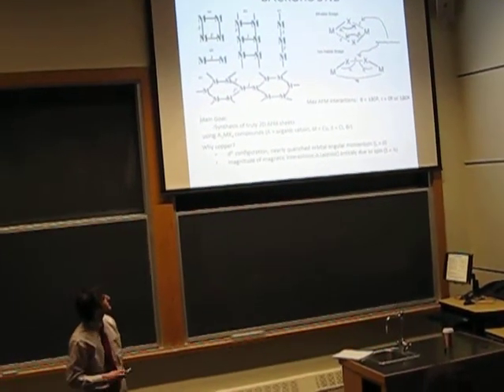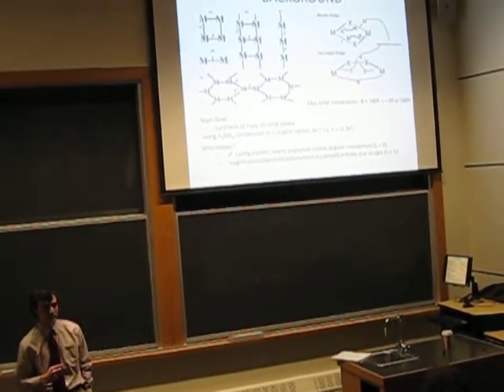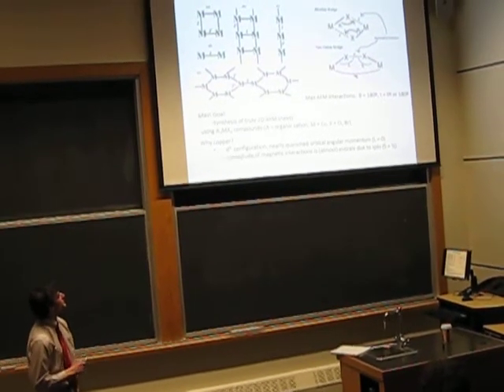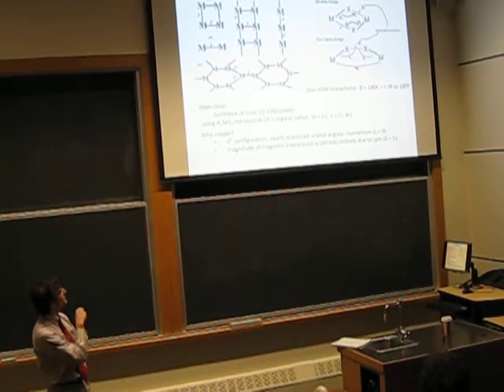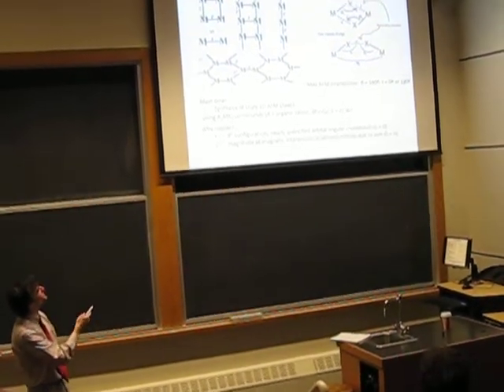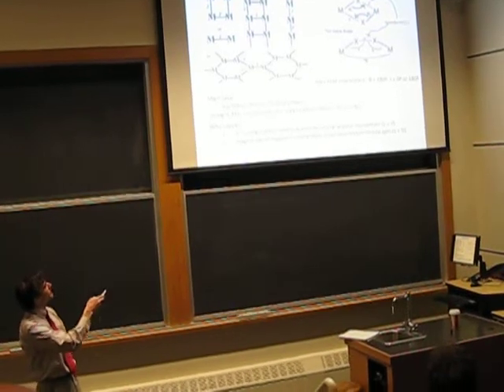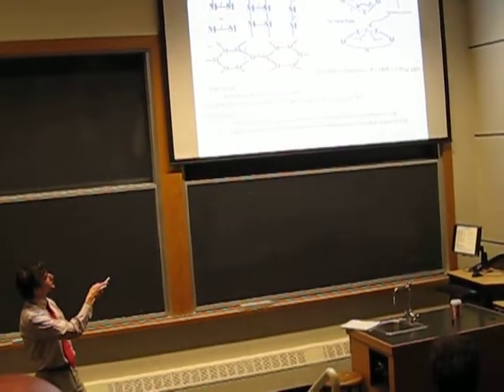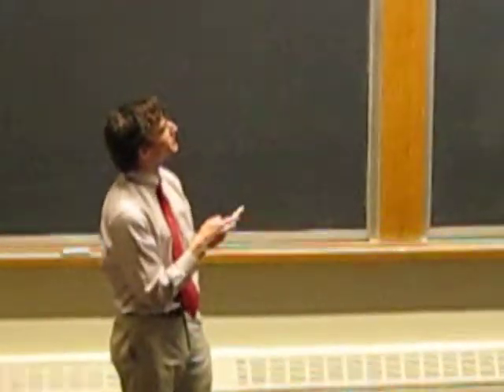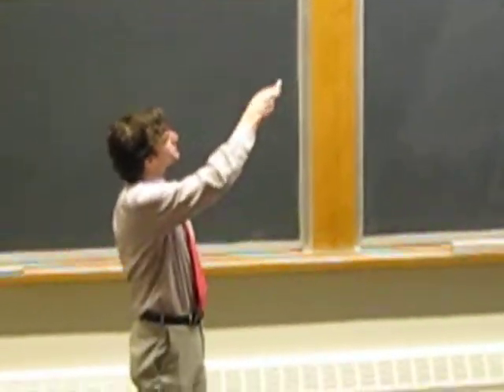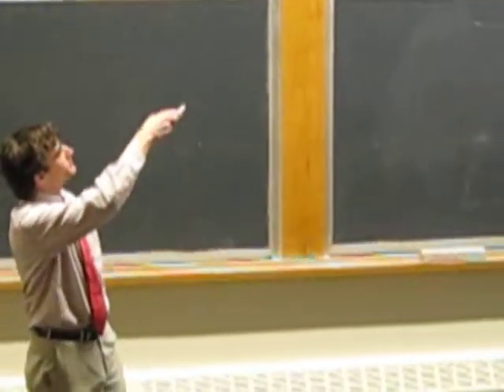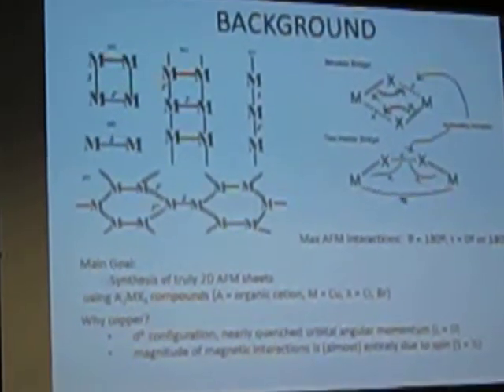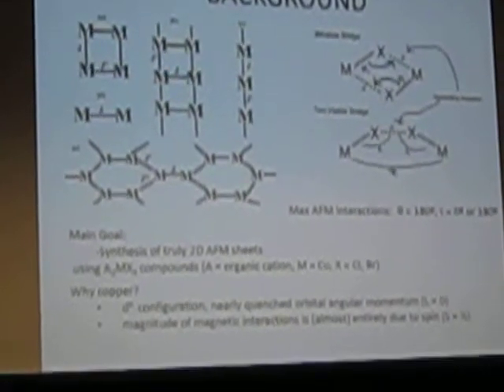M in this case is a magnetic ion, and the lines in between the M's are not bonds. They are simply interactions in the super exchange pathways. And there are two common super exchange pathways that we study in our labs, and that's the mono-halide bridge and the two-halide bridge. The main difference between the two is the number of non-magnetic atoms between the two magnetic ions. And typically, these are halide ions. X is halide, so either chloride or bromide. And then the metal in our cases is typically copper.